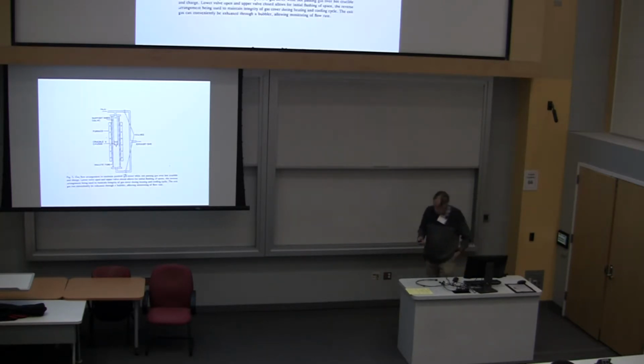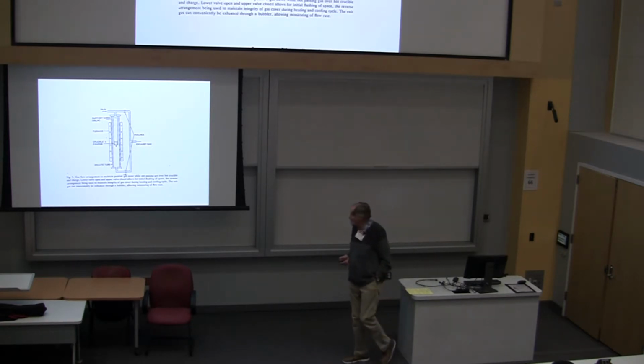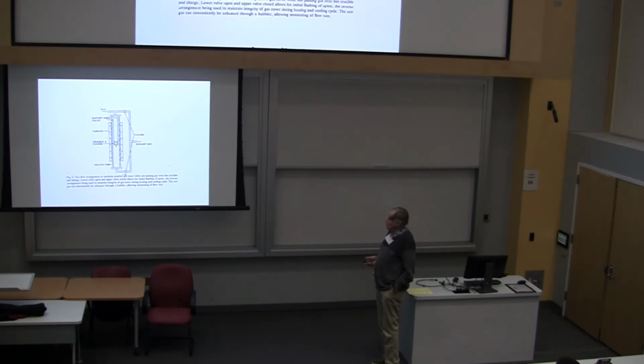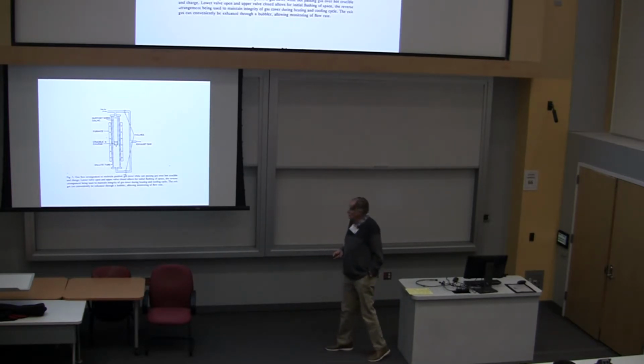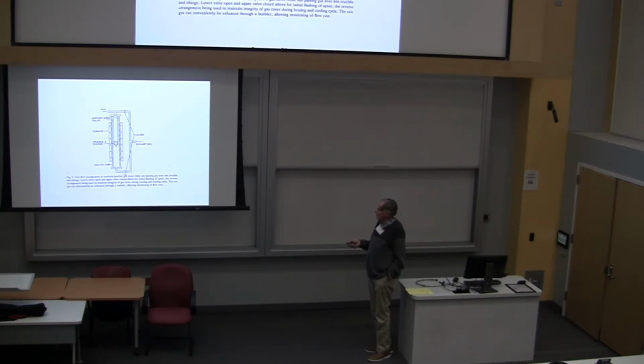The kind of arrangement that one uses to do this is to take a tube furnace and turn it on end and hang the crucible inside a ceramic tube that you have inert gas in. In other words, here's your high temperature tube furnace with a typically mullite or aluminum oxide ceramic tube. You can also stack crucibles in the bottom here up to somewhere in the middle of the tube and put your melt in there. And typically when one does these kinds of runs for flux growth, you fit 3-4 crucibles into this furnace.